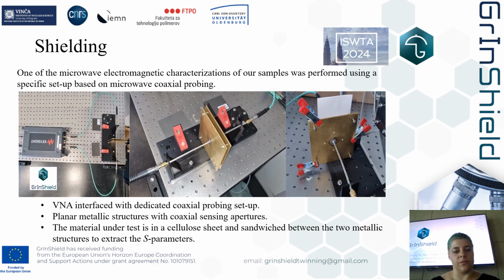So in our research, we have produced some freestanding graphene-based materials, both graphene oxide and reduced graphene oxide. And then we developed a setup for electromagnetic characterization for our samples, and it is based on microwave coaxial probing. It was done in Lille at IEMN, and it consists of a VNA interfaced with dedicated coaxial probing setups, planar metallic structures with coaxial sensing apertures, and what we did was we put the material under test in cellulose sheets sandwiched between two metallic structures, and then we measured S-parameters. We also did various kinds of different setups, both with our partners in Germany and in Lille. This is just one of the methods that we used.